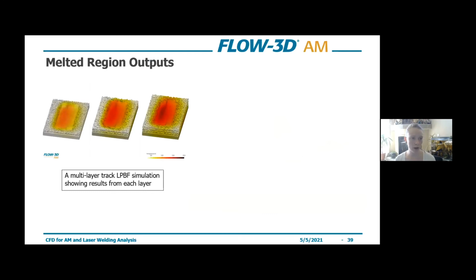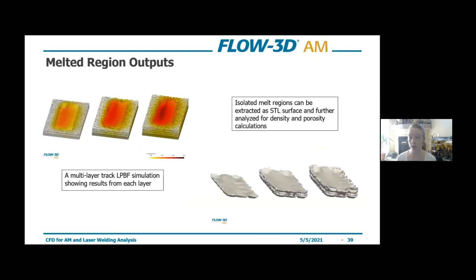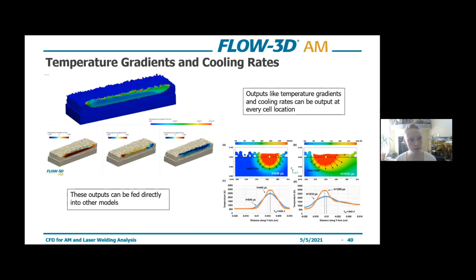And then we can also extract the melted region itself, as I mentioned earlier. And this is useful in understanding the effective part density, doing porosity calculations, understanding surface defects and morphologies. So there's a lot of information that can be gained just from extracting that melted region and neglecting the unmelted powder. And then we can also extract temperature gradients, cooling rates. So these are the outputs that are typically used to inform the next leg of analysis, whether it be microstructure or thermal stress evolution. So those are outputs that are readily available to you.